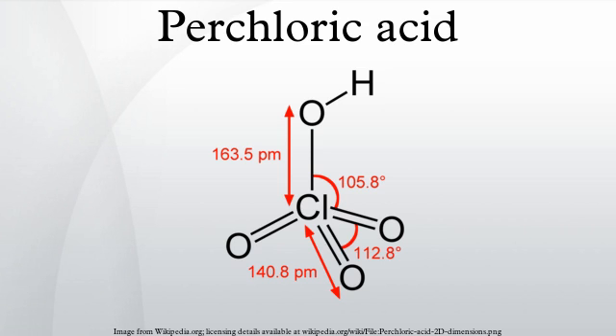On February 20, 1947, in Los Angeles, California, 17 people were killed and 150 injured when a bath consisting of over 1,000 liters of 75% perchloric acid and 25% acetic anhydride by volume exploded. The plant, 25 other buildings, and 40 automobiles were obliterated, and 250 nearby homes were damaged. The bath was being used to electropolish aluminum furniture. Organic compounds were added to the overheating bath when an iron rack was replaced with one coated with cellulose acetobutyrate, and a few minutes later the bath exploded.